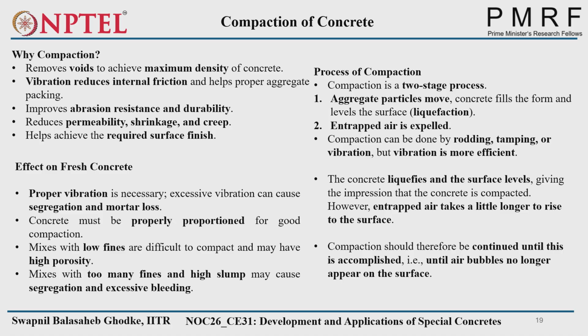Similarly, mixes with too many fines and high slump. Too many fines means either more paste content or more fine aggregate content. High slump will also be there, and if you provide excessive vibration, it will cause segregation and excessive bleeding. So you have to find the appropriate time according to your concrete matrix or the concrete constituents.